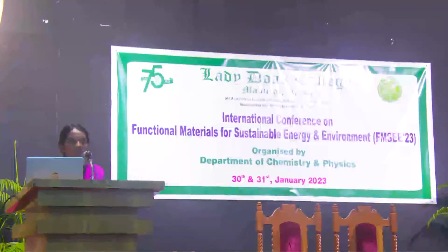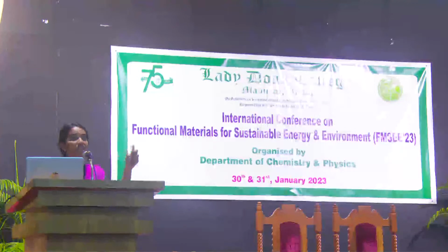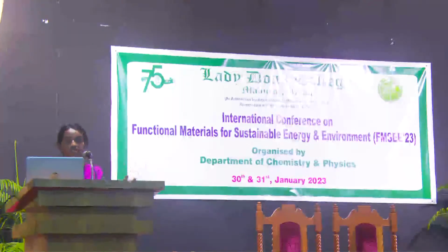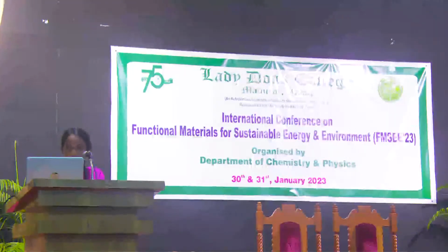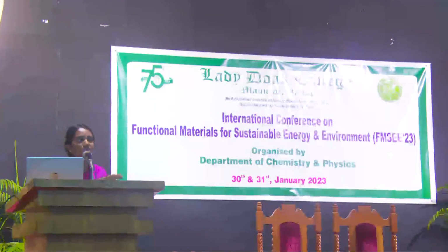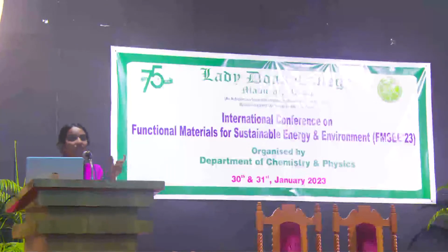From ATR analysis, the presence of a very broad peak at 3404 cm inverse, which corresponds to the OH of H2O molecules, confirms we prepared graphene oxide, which is a highly hydrophilic material. The other peaks confirm the carboxylic groups present at the edges of the graphene oxide nanosheet, and the carbonyl and hydroxyl groups present at the surface of the graphene oxide nanosheet. The nanosheet was confirmed from scanning electron microscope.